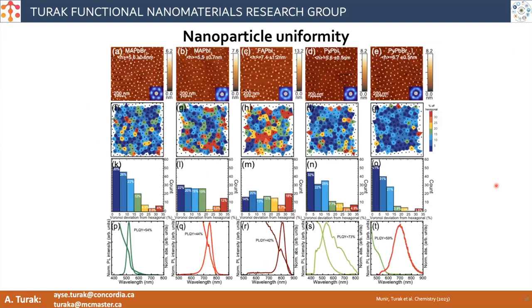The name of the game, though, is nanoparticle uniformity. That's what we're always aiming for. So here's an example of four or five different perovskite nanoparticles that we made recently with different compositions, but all of them have very, very similar uniformities in terms of their nanoparticle size. And the purity of their emission will vary depending on the material. These particular materials tend to be very broad in their emission.